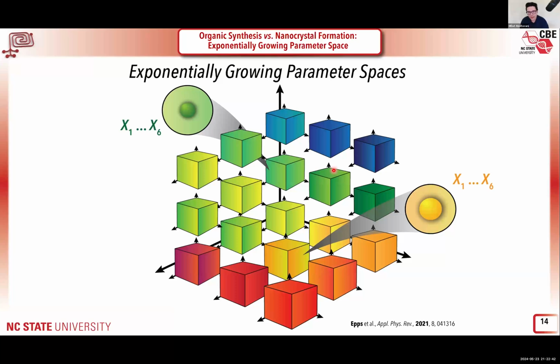But when you're doing inorganic nanocrystal synthesis, depending on how you heat or cool down, your monomer conversion rates are going to be different, your nucleation event is going to be different, and your growth rates are going to be different. So starting with the same ingredients, but just having different processing parameters, you're going to get different products. The product here is the shape, morphology, and optical properties of your nanocrystal. This makes inorganic nanomaterial synthesis extremely more challenging and difficult than organic synthesis, because you also have to think a lot about the processing profile, your temperature profile within your reaction. When you're doing organic synthesis, you only care about the temperature, not the profile.